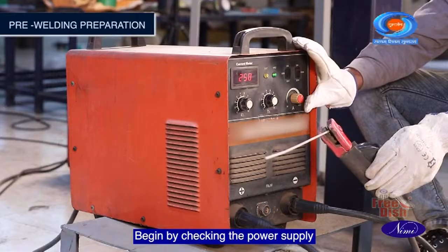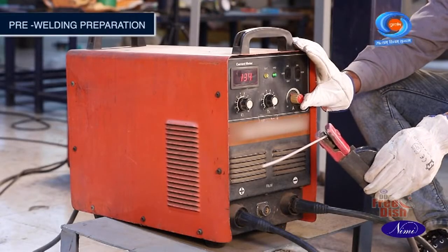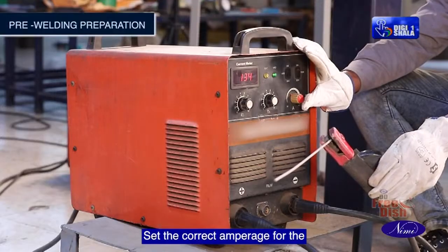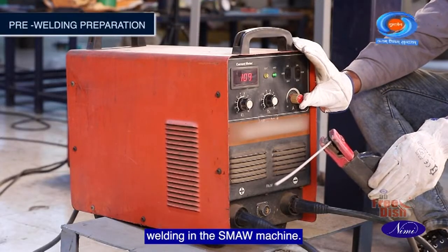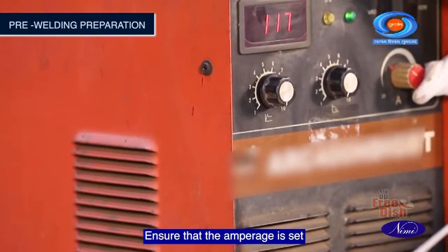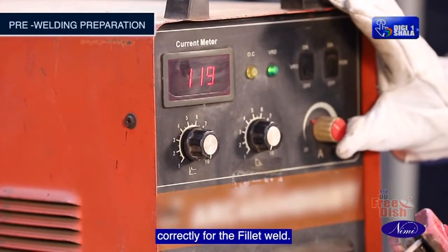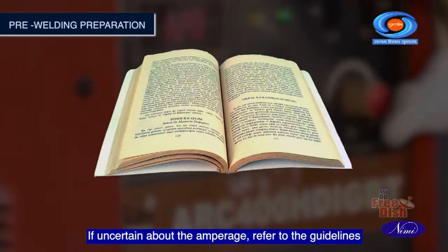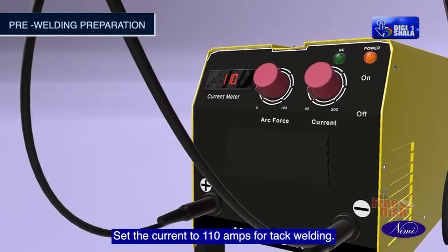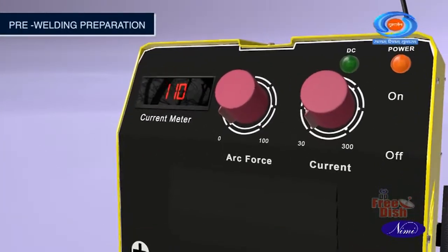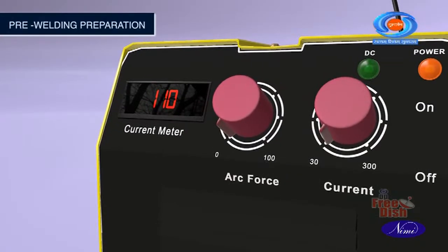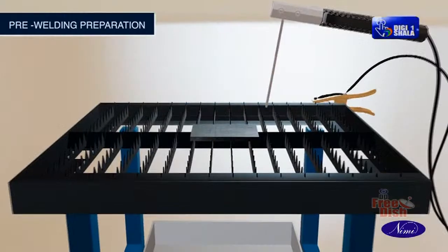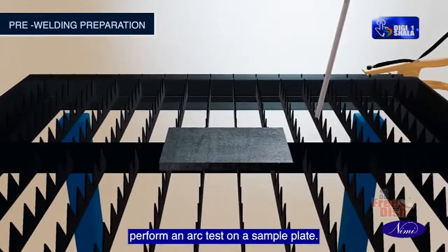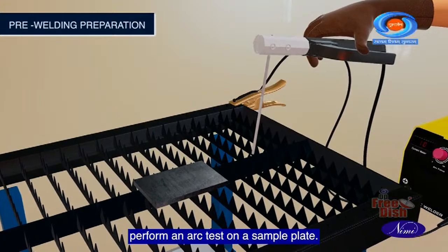Begin by checking the power supply of the SMAW machine. Set the correct amperage for the welding in the SMAW machine. Ensure that the amperage is set correctly for the fillet weld. If uncertain about the amperage, refer to the guidelines and adjust it accordingly for the welding process. Set the current to 110 amps for tack welding. If the machine is functioning properly, perform an arc test on a sample plate.